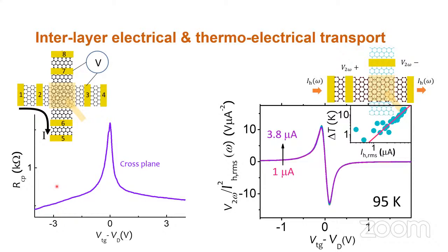We measure the two temperatures independently by measuring the 4-probe resistance of the individual layers. We measure at different points of the graphene. So I'm guessing that if it had been a difference within the layer, it would have come out if you measured at different points of graphene, which is not the case. I hope that answers the question. I got your point, yeah.